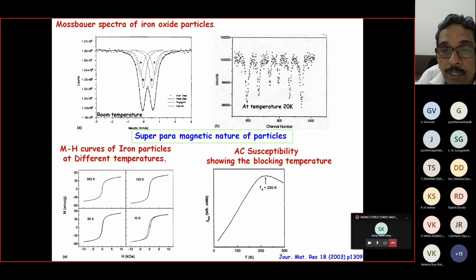at that time we had some limitations wherein we could not really see the actual particle size and do much in the electron microscope. But through alternate methods, I am trying to establish that I have synthesized a nanostructured material which is about 20 nanometers. So this is how science progresses. It was already 19 or 20 years back that we carried this out, or even more than that.